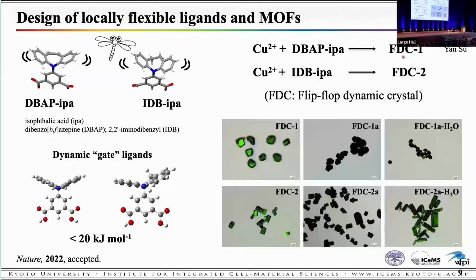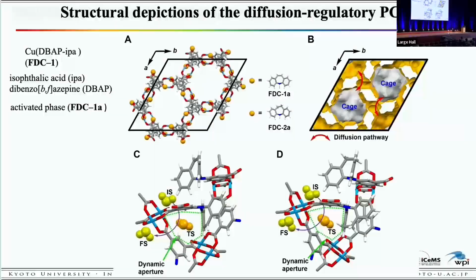So we synthesize the framework using copper 2+. The first one we call FDC1, the second FDC2. FDC means flip-flop dynamic crystal. The synthesized FDC1 possesses a cage structure. Cages are connected to the local gate of DBAP. Subsequently, FDC1 was subjected to vacuum at 393 Kelvin, resulting in its activated phase, FDC1A.